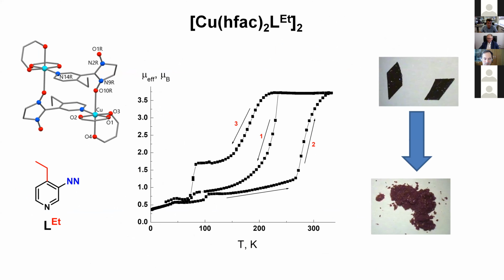The most interesting complex was obtained with ethyl-substituted nitroxide. Despite the fact that the complex has a structure analogous to the complexes mentioned above at room temperature, investigation of the magnetic properties revealed a non-trivial temperature dependence of the magnetic moment. The value of the magnetic moment at 300 Kelvin is about 3.7 Bohr magneton, and during the first cooling cycle it practically does not change to a temperature of about 230, after which it sharply decreases, reaching 0.9 Bohr magneton at about 90 Kelvin.